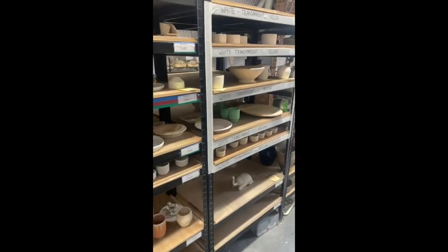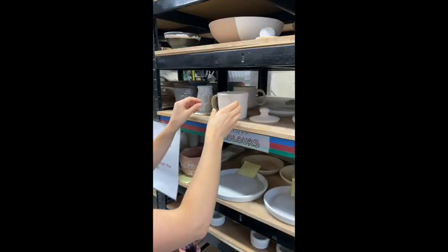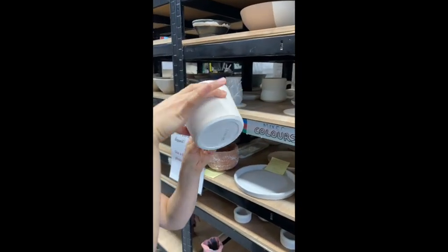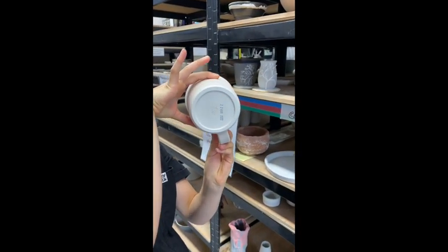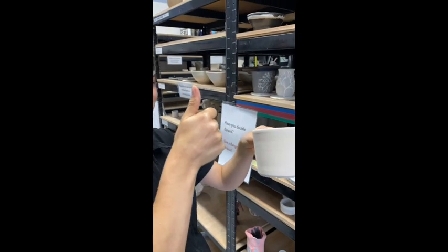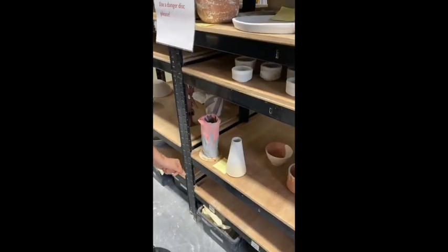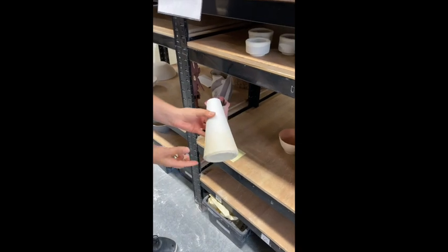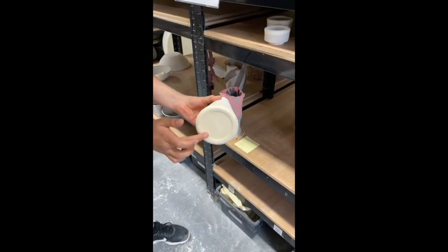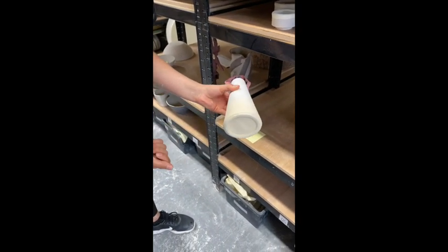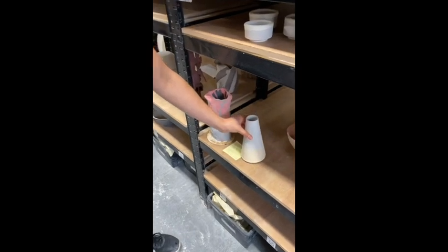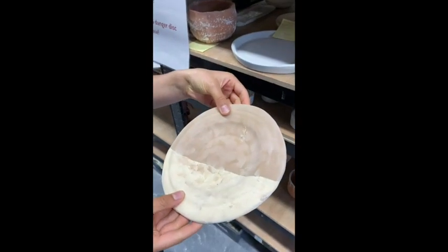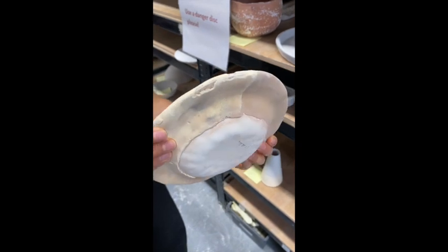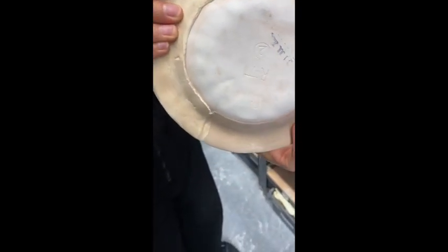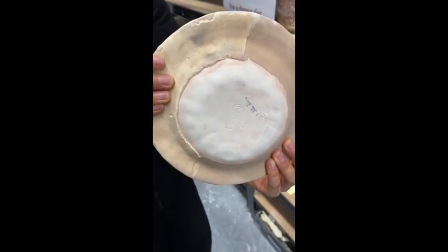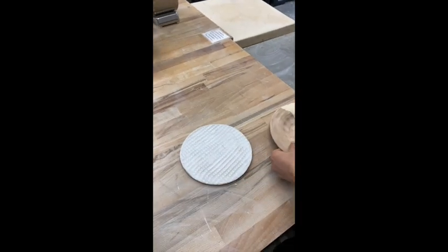Having said that, the same rules apply for the props. When choosing work to go into a glaze pack, make sure that the bases of each piece are totally clear of any glaze powder. If there's glaze on the bottom, it will cause the pot to stick to the shelf, therefore ruining the pot and the shelf. If you notice that there is a thick layer of glaze on the pot, it has been double dipped, or you are in any way concerned about the glaze running, please place a danger disc under the pot to protect